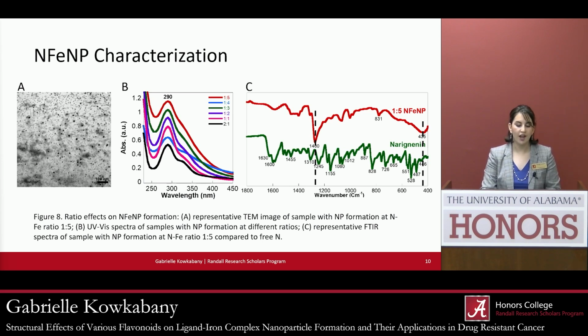in naringenin. However, the UV-vis absorption spectra actually didn't really demonstrate that anything happened at all, which was quite curious to me because when we did this with quercetin, there was a clear shift in the peak, but you can see that the peak is around 289, 290 like it was for naringenin by itself. And I hypothesized that the reason that this is this way is because naringenin lacks that double bond in its middle ring structure, and so therefore when iron chelation occurred, there was actually no electron transfer happening. That resulted in no shift in the UV-vis absorption spectra, which is why it's still around that 290 peak.